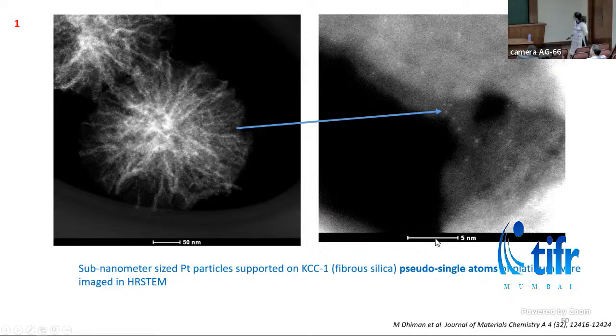If you look at the scale bar, this much is 5 nanometers. That means that every small bright spot which you see is 100 picometers in size. So this kind of imaging cannot be done using any other microscope. This kind of imaging needs a probe corrector microscope if you want to image at this scale or this level.